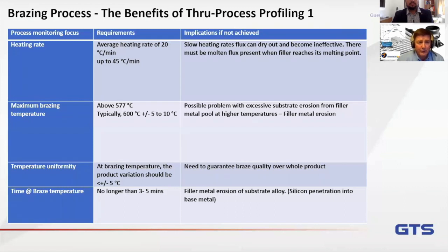Uniformity across the product is essential, and typically we're looking for a spread of less than plus or minus 5 degrees Celsius over the product itself. Now, you've got to be careful, and we'll talk about this on the next slide or two. When you think about the way that the radiator is constructed, there are going to be areas where there's bulky metal for the fixture of the radiator, which might be hindering the heating rate of the actual fins in that vicinity, and therefore maybe selectively affecting the brazing in particular areas of the product, which you need to be careful about.